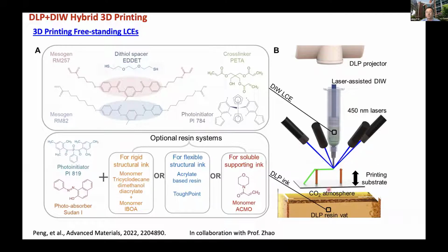we want to avoid interference between the laser and the DLP reservoir, because you don't want the laser to cure the DLP during the printing. So in this case, we pick a 450 nanometer laser, and for the LC, we also pick a photo initiator, PI 784, that has an absorption coverage between 300 to 450 nanometers. So the laser would cure the LC. But for the DLP resin, we're using the photo initiator A19, which is typical people use. And if you look at the absorption spectrum, A19 would not absorb light at 450 nanometers.